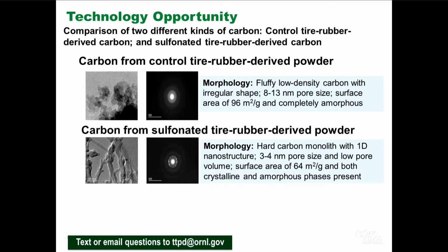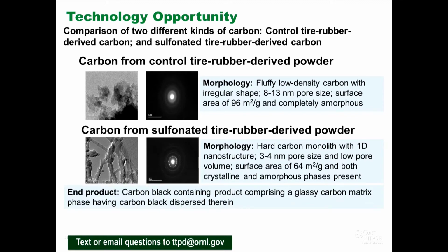Let's compare with the sulphonated tire rubber derived powders. It is more like a hard carbon monolith with a one-dimensional nanostructure, with 3 to 4 nanometer pore size and low pore volume. This has a surface area of 64 square meters per gram, and in the selected area diffraction pattern both crystalline and amorphous phases are present, compared to our control sample. The end product is a carbon black containing product comprising a glassy carbon matrix phase having carbon black dispersed in it. That's the end product when you go through the sulfonation followed by the pyrolysis process.